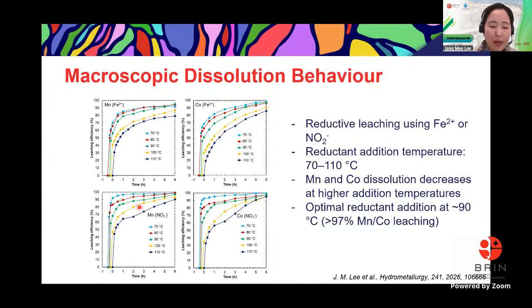So as you can see here, when the reductant was added at lower temperature, especially between 70 to 90 Celsius, manganese and cobalt leaching efficiencies become higher as compared to 100 Celsius and 110 Celsius. However, when the reductant was introduced at the higher temperatures, 100 and 110, the leaching efficiencies of manganese and cobalt were lower.